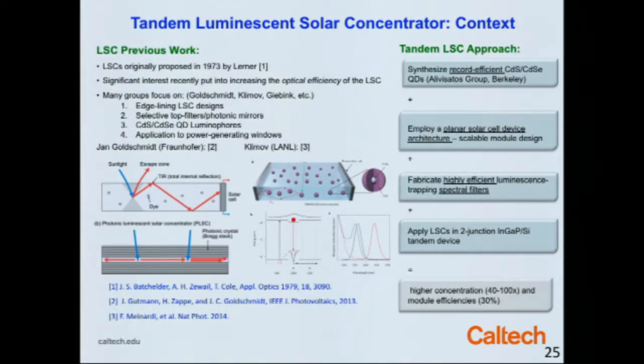Historically, people began work on this back in the mid-1970s, during the first energy crisis, using organic dyes. That was a sensible thing to do at the time—we didn't have quantum dot technology. But the organic dyes had luminescence efficiencies of at most maybe 60 or 70%, and they were quenched relatively easily, so we were never able to get concentration factors beyond about a factor of 5 or 10.